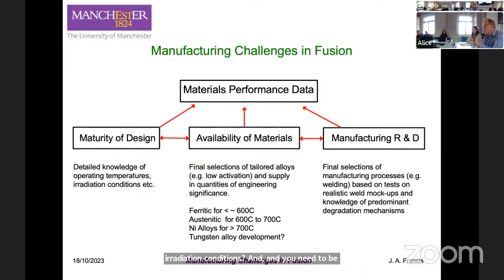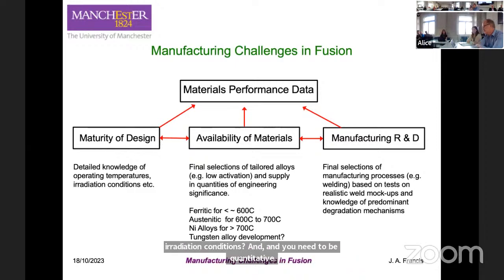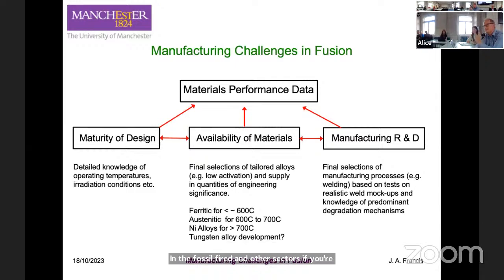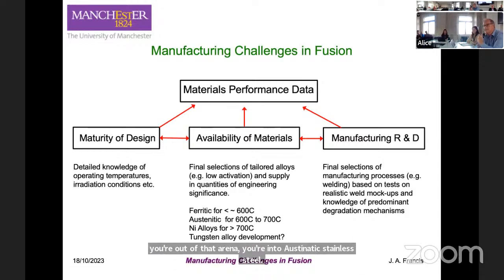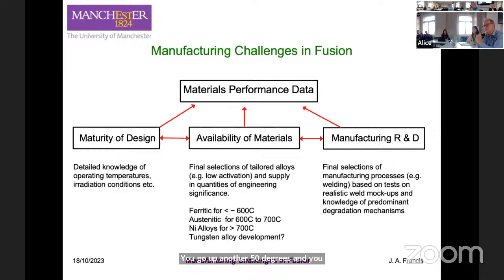In the fossil-fired and other sectors, if you're operating up to about 600 degrees C, you can consider a ferritic steel. But if you push that up to 650, you're straight away out of that arena. You're into austenitic stainless steels. You go up another 50 degrees and you're starting to look at nickel-based alloys, just based on their performance in creep and against other degradation mechanisms.